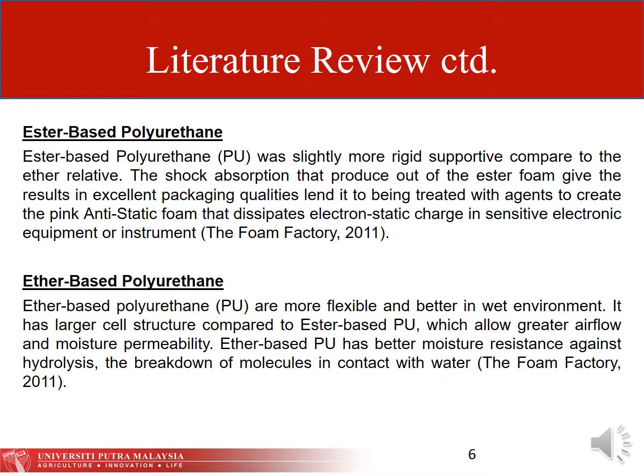Ether-based polyurethane is more flexible and better in wet environments. It has a large cell structure compared to ester-based polyurethane, which allows greater airflow and moisture permeability. Ether-based PU has better moisture resistance against hydrolysis, the breakdown of molecules in contact with water. In conclusion, ether-based polyurethane has more water-resistant characteristics compared to ester-based polyurethane.